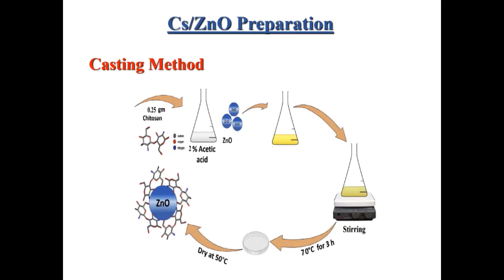For chitosan zinc oxide nanocomposite, we prepared 5 different percentages of zinc oxide with chitosan from 10% to 50% of the weight using the casting method by dissolving chitosan in distilled water with acetic acid, then adding zinc oxide to the solution before casting.